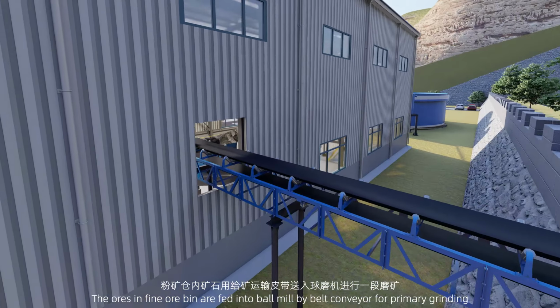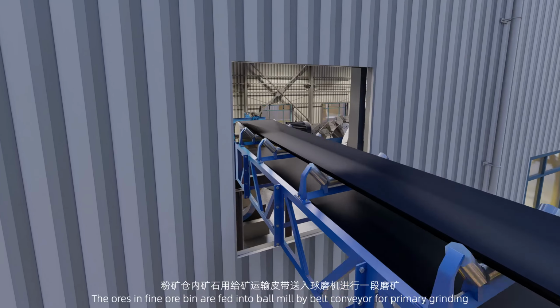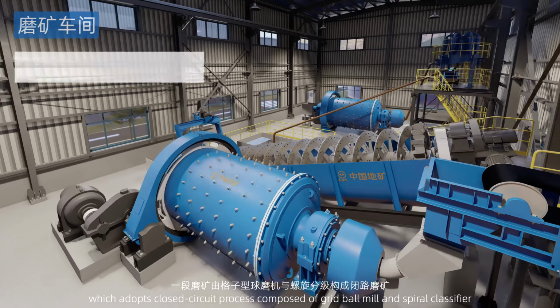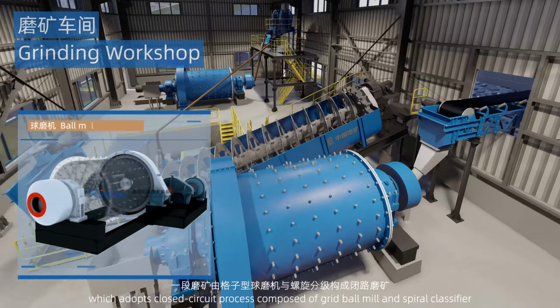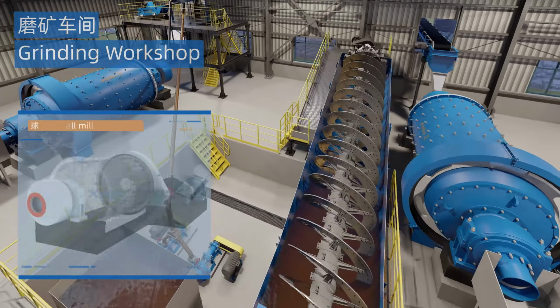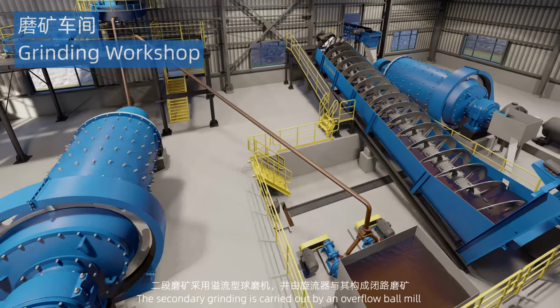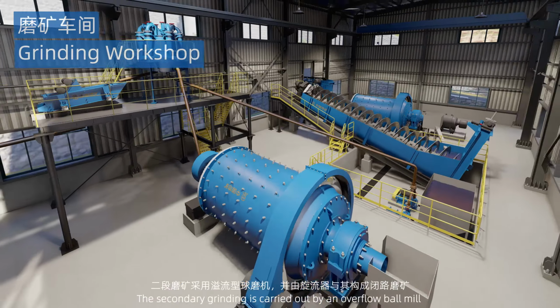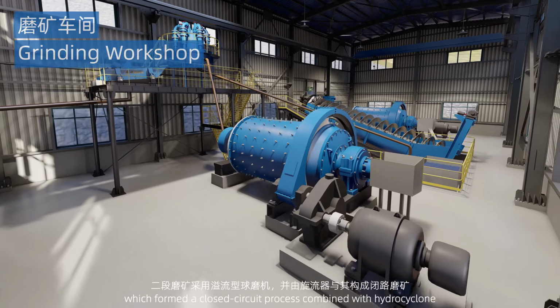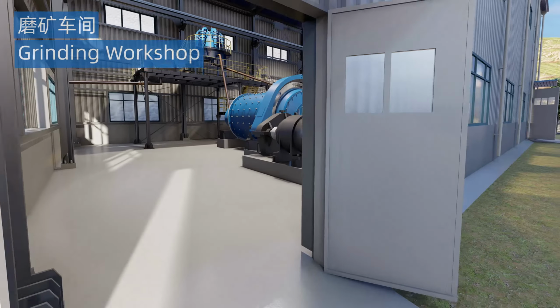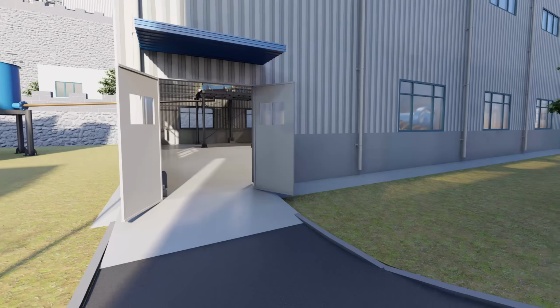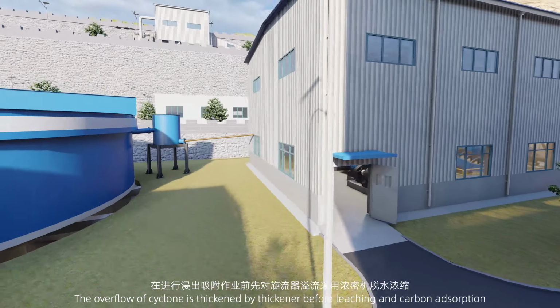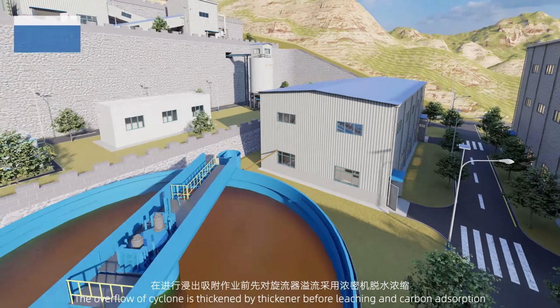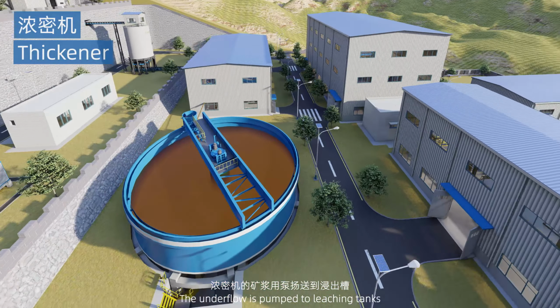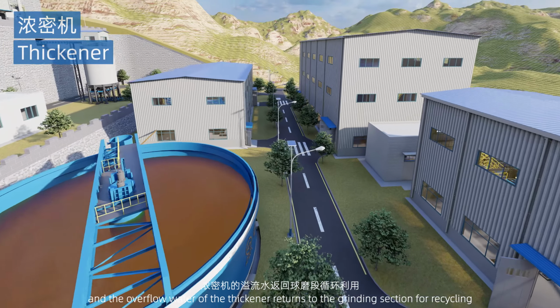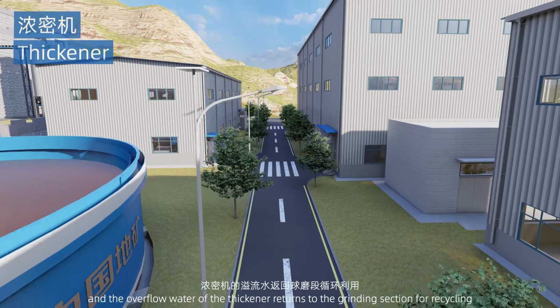The ores in the fine ore bin are fed into the ball mill by belt conveyor for primary grinding, which adopts a closed circuit process composed of a grid ball mill and spiral classifier. The secondary grinding is carried out by an overflow ball mill, which forms a closed circuit process combined with a hydrocyclone. The overflow of the cyclone is thickened by a thickener before leaching and carbon adsorption. The underflow is pumped to leaching tanks, and the overflow water of the thickener returns to the grinding section for recycling.